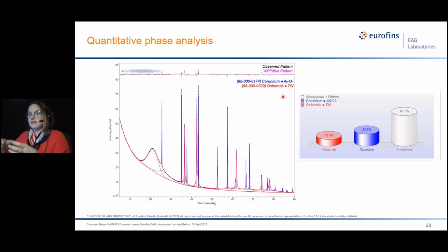So it's refining the peak intensities relative to each other, the peak widths based on crystallite size, and there's a lot of other variables that you're refining to make sure that you are getting the correct percentages. This is that same pattern that I showed before, and you'll notice this very broad peak is amorphous material. So we can't tell what the amorphous material is. I know what it is, it's glass. So I knew what the exact density is.